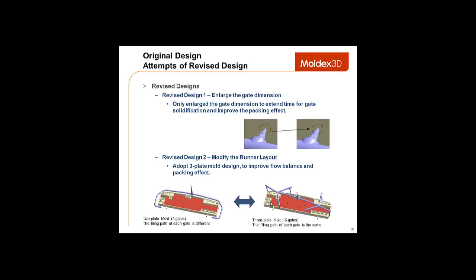For the first revised design, we decided that we should enlarge the gate dimensions to extend time for gate solidification and improve the packing effect. In the second redesign, we modified the runner layout to improve flow balance and the packing effect.